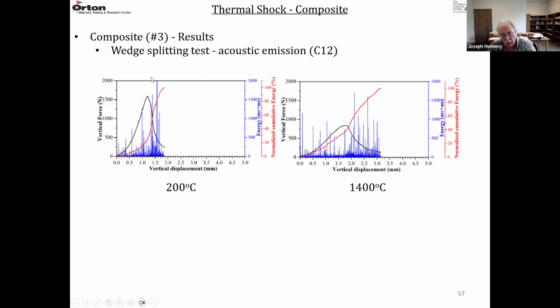So at the same time they were doing the digital imaging, they did acoustic emission. And this is vertical force versus vertical displacement. So force versus strain, basically, at 200, 1400 for C12. The acoustic peaks, each one of these vertical lines is an event that takes place. So when you propagate a crack through a coarse grain or a matrix interface, it makes a noise, you pick it up with acoustic emission. The higher the peak, the more energy involved in that crack and that crack movement.